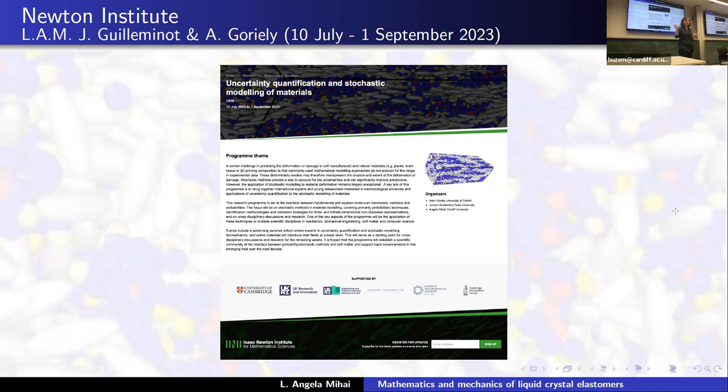So then, if you add the extra component with the liquid crystal component, that's captured. We have actually shown that in the paper with this molecular dynamics simulation. It's captured very well, and in an interesting manner. Measuring the different elastic moduli in different directions does give you different results. So the two components together give a more accurate representation of the material than without the nematic component. At large strain, the classical model is not capable of capturing it, so you need more of an Ogden type. At least that's what we conclude.